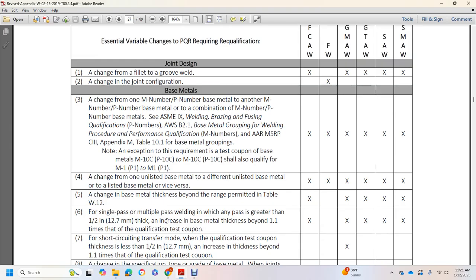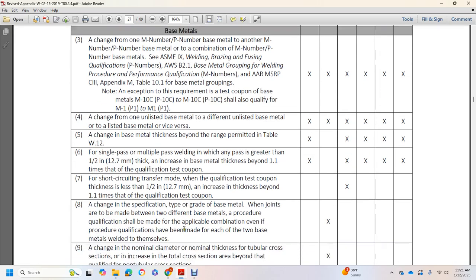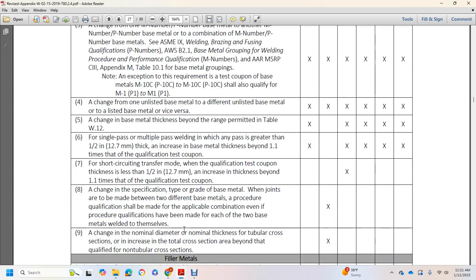Change in the base metal thickness beyond the range permitted with Table W12. For single pass or multiple pass welding, any pass greater than 1/2 inch thick, an increase for the base metal thickness beyond 1.1 times the qualification test coupon. For a short circuiting transfer method, the qualification test coupon thickness is less than 1/2 inch, an increase in thickness beyond 1.1 times the qualification test coupon.